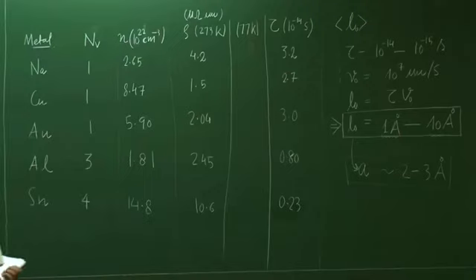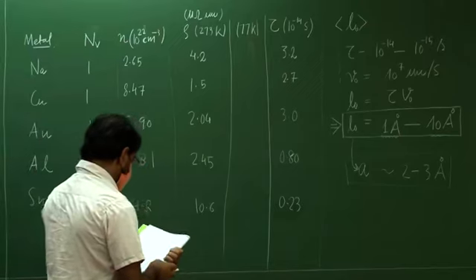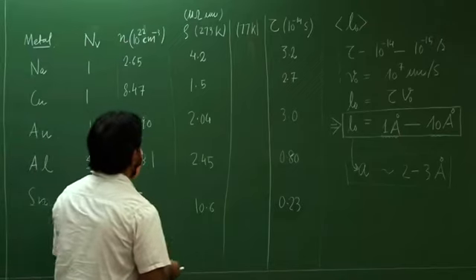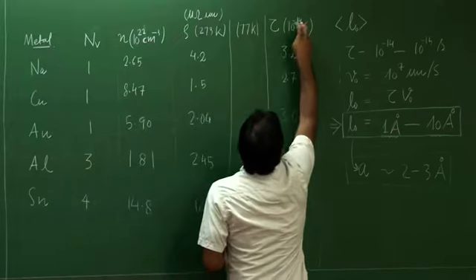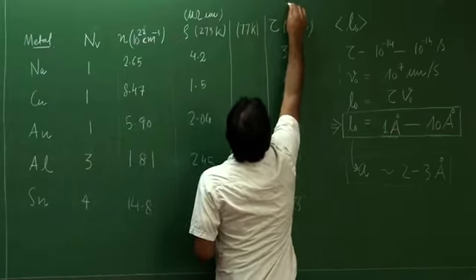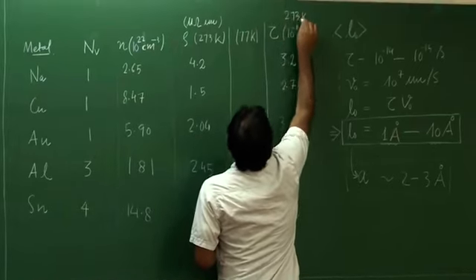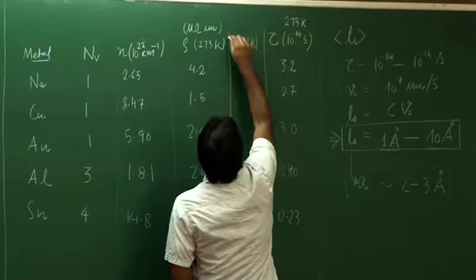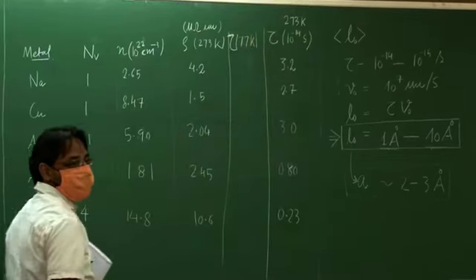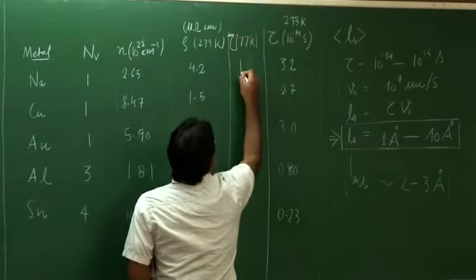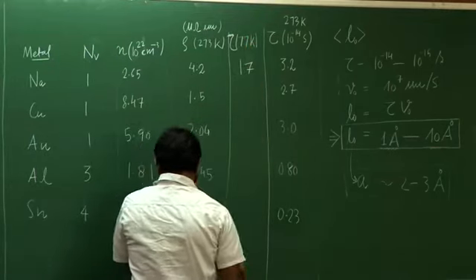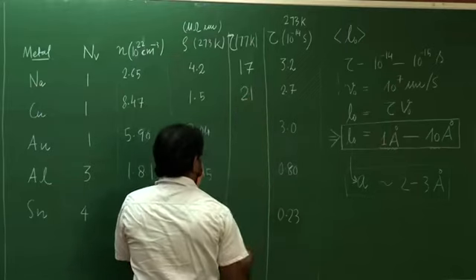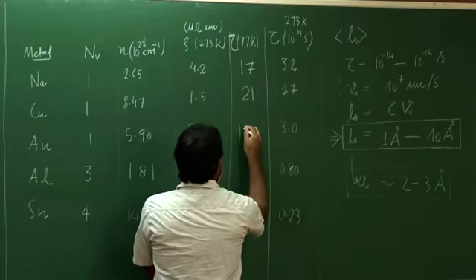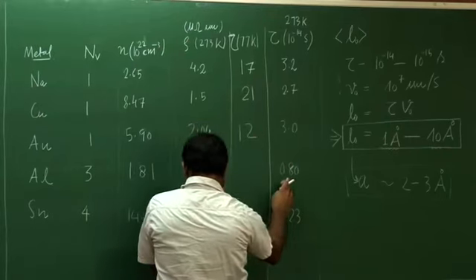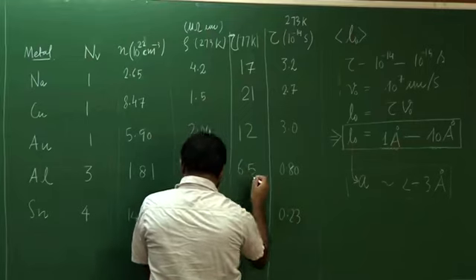with Drude's model. So if we look at the relaxation time, the relaxation rate, this is the relaxation rate at 273 Kelvin. Now we are again looking at tau, but tau at 77 Kelvin, and this number comes out to be 17. This number comes out to be 21. This number 3 has become 12. The number 0.8 has become 6.5. And the number 0.23 has become 1.1.